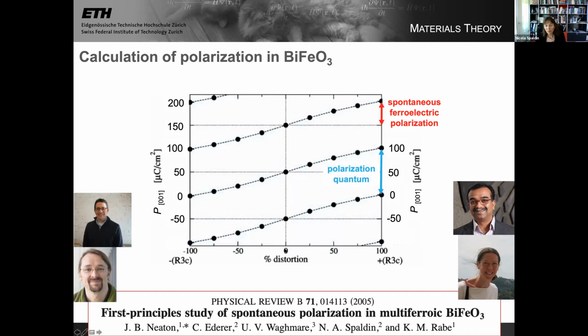Okay. Then when we gradually allow the structure to distort to its ferroelectric structure, you see that the polarization evolves from the value in the undistorted structure. And whichever branch on this polarization lattice we choose to evolve from, whichever unit cell, if you like, we pick to evaluate the polarization, we have exactly the same evolution. And the measurable bit that we measure if we do a switching experiment, what we call the spontaneous ferroelectric polarization, that's the difference between the ferroelectric and paraelectric values. That's the same in every case, right? And so whichever of these branches we measure or we calculate along, we get the same value for the spontaneous polarization.